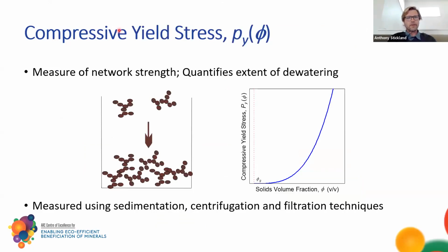So for the compressive yield stress, or the compressive strength, this parameter, as I said, quantifies the extent of dewatering. It's what happens at really long times. Here I've got a picture of what happens if some flocs are settling, and you can see that these flocs form big open space-filling networks. If I apply a pressure to that, it makes it collapse. So this looks something like this. The compressive yield stress as a function of volume fraction, phi 0 at the gel point, typically increases with a power of about 5.